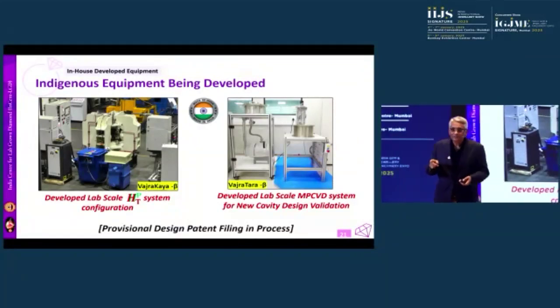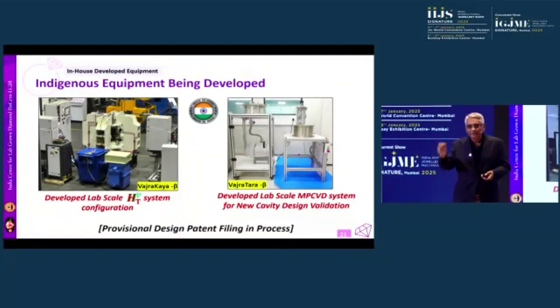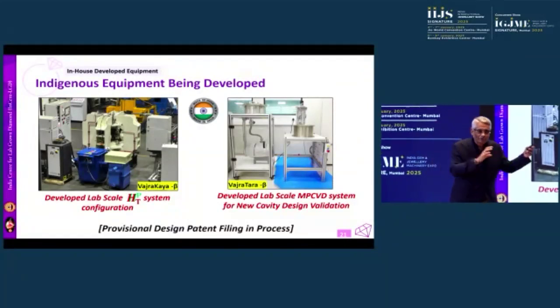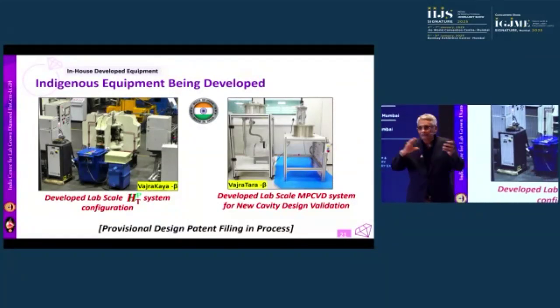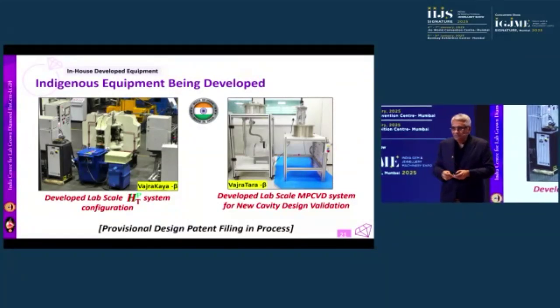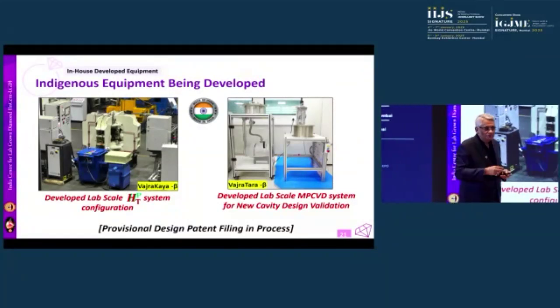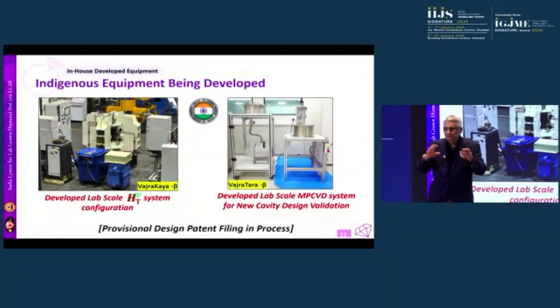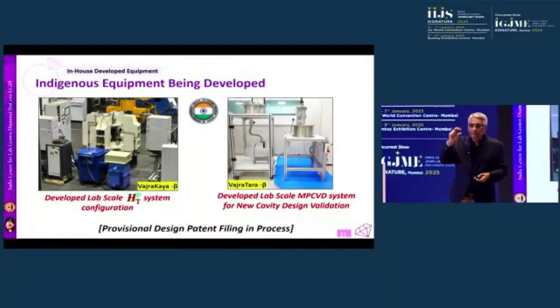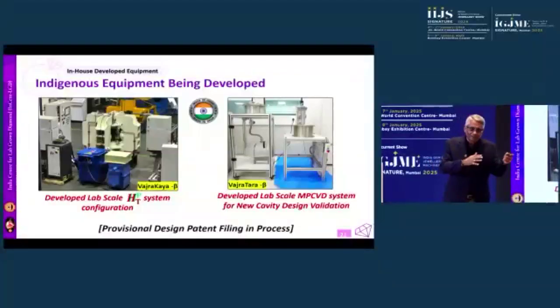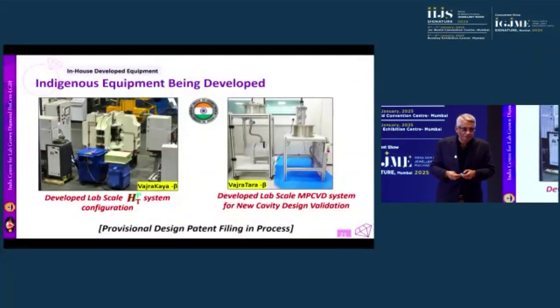HPHT machines are also used for treatment. Treatment is a small process. You grow diamond using CVD and then transfer it to your HPHT machine. Treatment is a 3 to 5 minutes process. It's not a big deal. But if you want to grow a big diamond using an HPHT process, it's exactly like CVD. It takes 10 to 15 days.